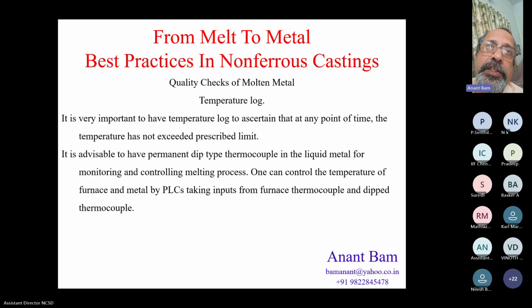And the range should be set in such a way as to allow a certain buffer zone. Because the furnace lining is usually at 900 or 1000 degrees Celsius, the coil temperature. The metal is at 730, 740, 720 degrees Celsius. So the delta T, the temperature difference, is to the tune of 250 to 300 degrees Celsius. The formula for heat transfer is mCp delta T. So m is the mass. The mass of the lining, if it is Kaowool lining or ceramic foam lining, is very small, maybe 100 kg or so.